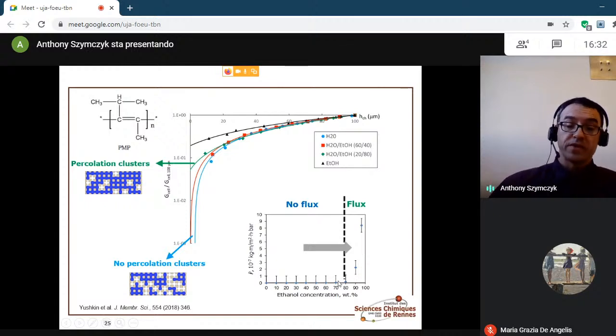This was interpreted by saying that adding a certain amount of ethanol allowed the clusters of liquids absorbed by the membrane to connect with each other and thus to generate percolation clusters, allowing liquid transportation through the membrane. Electrical conductance measurements performed in tangential mode confirmed this hypothesis.